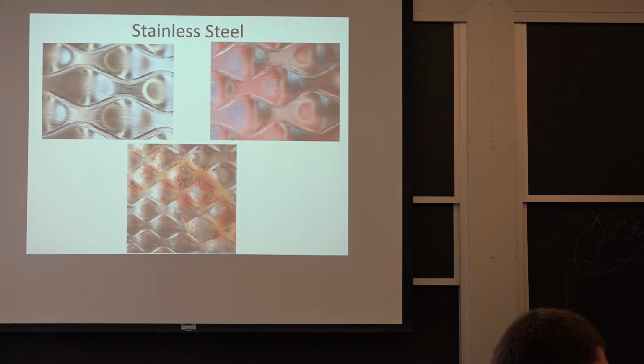Speaking of stainless steel, the word says it's stainless, but it will still corrode under certain conditions. In the ground, it can corrode as fast as regular steel. So what do we do about that? There are different ways. This is just flashing, and you have that on some museums, some fancy homes. Stainless steel flashing that, because of exposure to the mist from the ocean, just starts to pit and corrode. It doesn't really lose thickness, but it definitely loses the appearance. And one way to mitigate it was to put a very thin acrylic base coating on it.